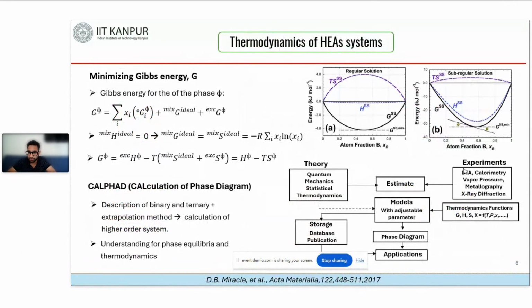Before going deep into the CALPHAD modeling, I want to discuss the thermodynamics of high entropy alloys and also the CALPHAD modeling. The CALPHAD models work on the principle of minimizing Gibbs free energy. The Gibbs free energy of any phase can be defined as a summation of the Gibbs free energy of the individual constituent phases, the ideal Gibbs free energy of mixing, and the excess Gibbs free energy. While considering our modeling, we consider the pure element as the standard state, so the constituent Gibbs free energy of the constituent phases